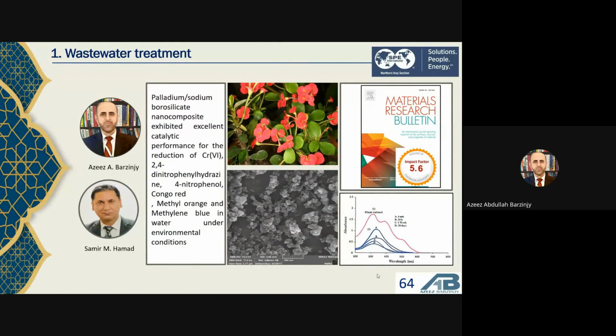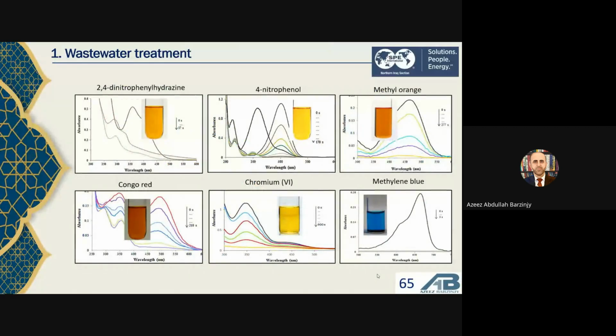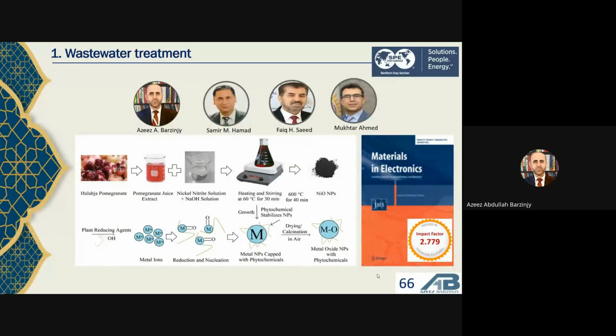So here are some examples of our work. In this work, we utilized nanoparticles for reducing chromium-6, which is very carcinogenic, available inside the water, and we also degraded different types of dye, such as methyl orange and methylene blue, in water under environmental conditions. So here you can see the time of the degradation for different types of dyes, and also the reduction of chromium 6 to chromium 3, which is much safer than chromium 6.